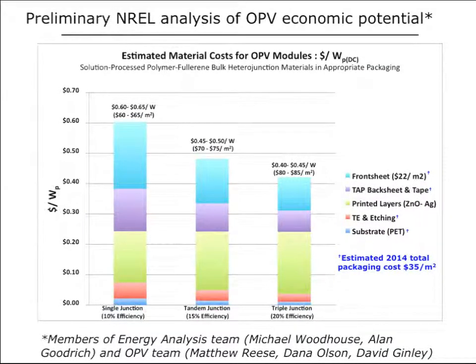So if one projects forward a couple years to the point where the barrier materials have come down in cost, and this is projections now for the year 2014, and this includes both the active layer materials and all of the front and back cladding layers, one can think about cost below $1 per watt for the materials of the device. There are no production costs in this quite yet. So for single junction, we think about 60 cents per watt, double junction, something like 50 cents, and even lower for triple junction if we go that far. So some promising economic potential for the OPV.